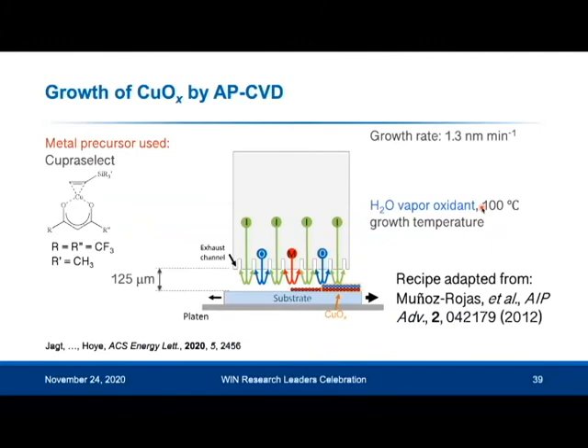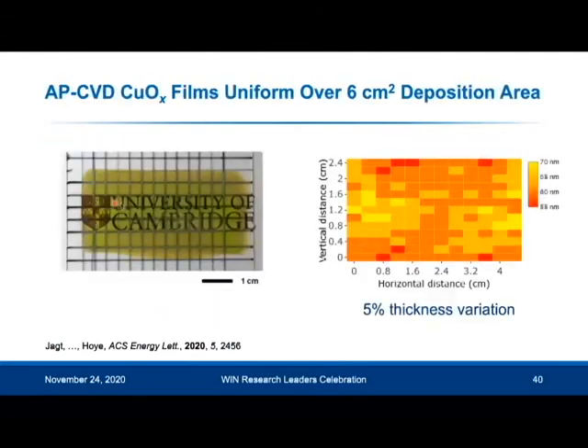Okay, I'll just move more quickly. So this is the setup for our APCVD reactor for growing the P-type oxides. We use Cupra Select as our metal precursor. And here you can see a photograph of the films, and you can see it was uniform over the 6 centimeter squared deposition area, and the variation in film thickness was only 5% of the mean.